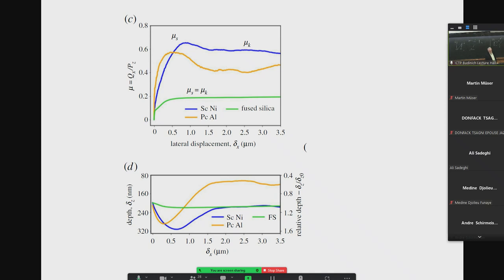This is static friction. So essentially what you've got here is an increase in static friction, purely because you've deformed the surfaces, you've generated a few little cuts, and then to get out of that requires some force which is higher than once you actually start making a continuous groove. Kind of useful to know if you're worried whether your car tires are going to slip, as was mentioned.